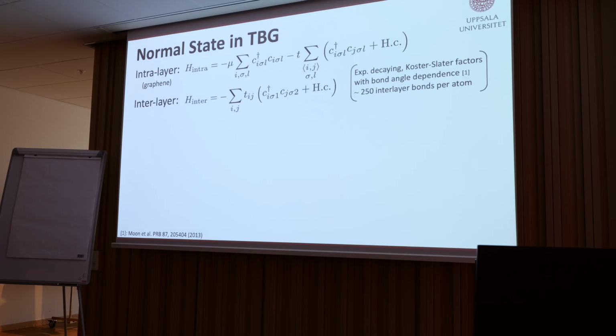And the normal state is pretty easy to model. The intra-layer is just graphene, so it's enough to have a nearest neighbor hopping. Here l labels the layers. You have two layers, and in each layer I have just nearest neighbor hopping. I have some chemical potential that I can use to shift the doping in the material. And then I couple these two layers with this interlayer term, coupling layer 1 and layer 2. I can calculate this hopping parameter as exponentially decaying, with factors that capture the bond angle dependence.